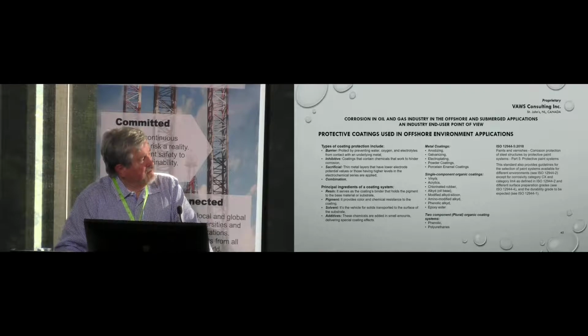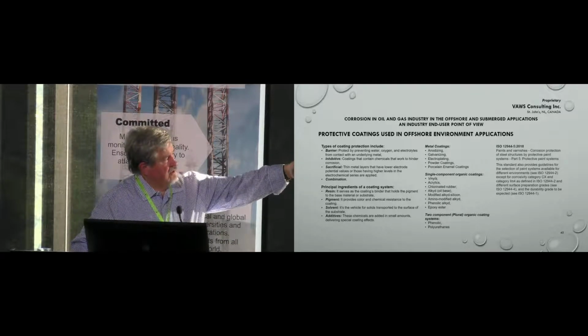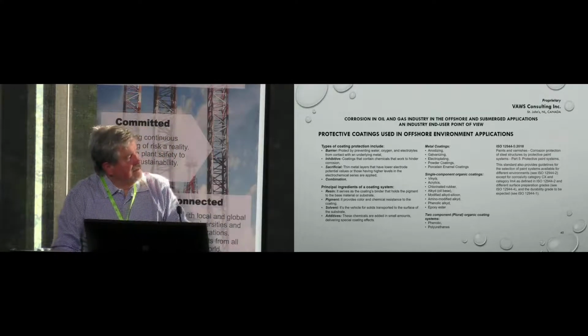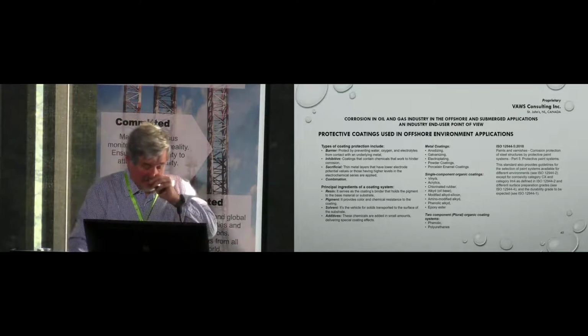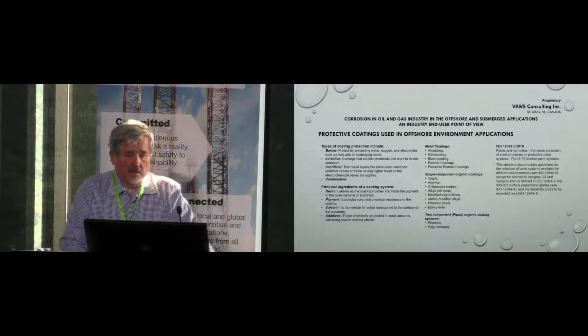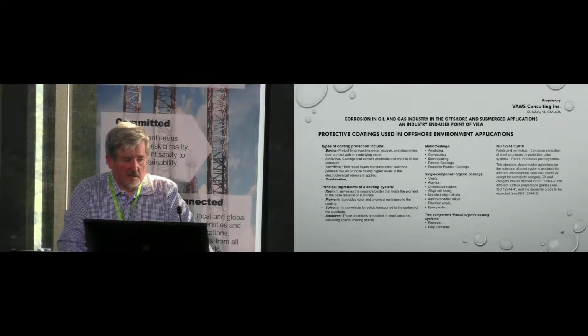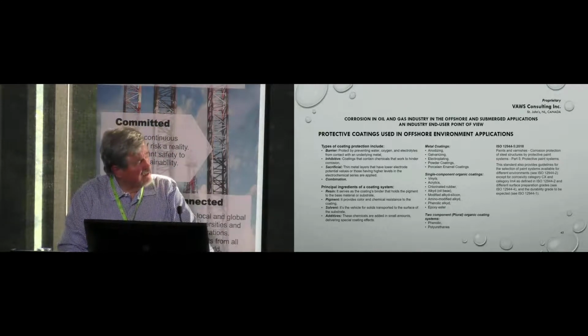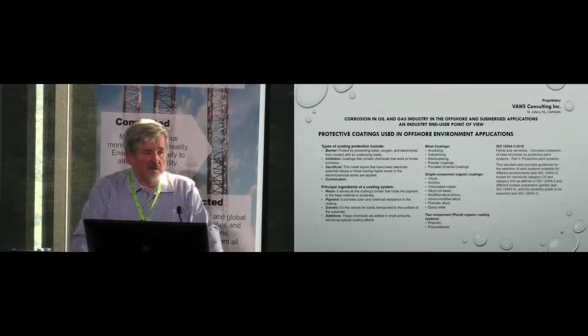So how many coatings do we have? We have tons of coatings. Basically, they are barrier coatings, inhibitive, sacrificial, or a combination of these. And zinc hot-dip galvanizing is still the best coating in the world. I don't know if you had a chance, or if you will have a chance, to go to the marine facility in Halifax Harbor where they do training for people who go offshore. That structure was built about 15 years ago, before I visited. It looked bright new, like they did it yesterday, and it was hot-dip galvanized. But it's not a solution for all, because the structures they make these days are huge and you would need really huge facilities to do that.